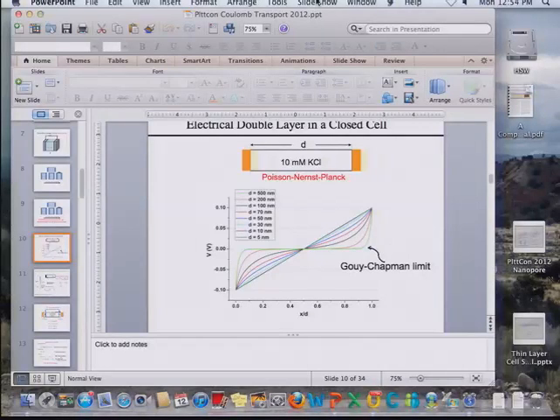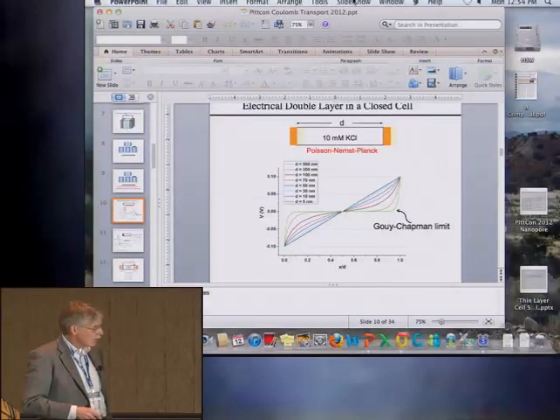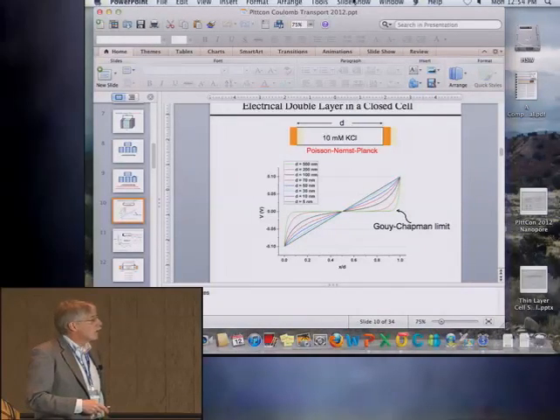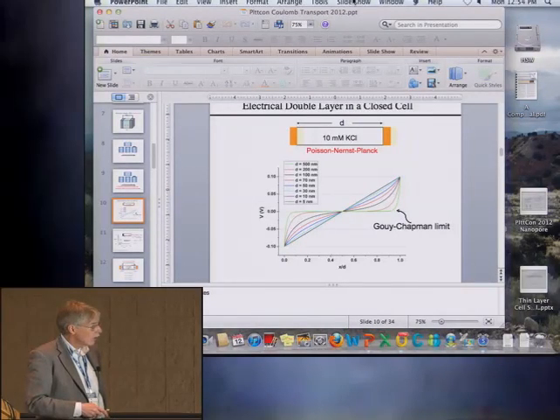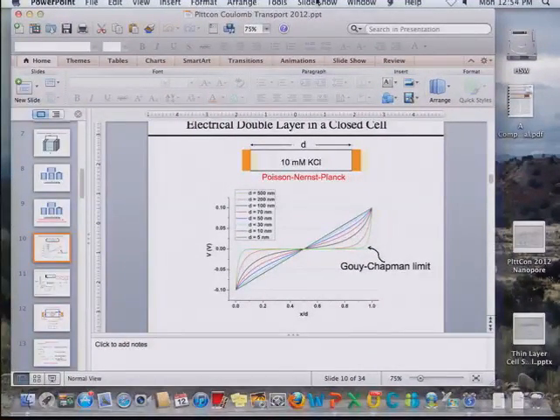All right, if you calculate the potential profile, this is voltage or potential versus distance for a cell that contains 10 millimolar potassium chloride. These are real calculations. And I'm plotting the distance across the cell normalized to the thickness of the cell. That's why they all look the same. But a very wide or large cell, 500 nanometers, is this one right here. The green curve comes down, and it's over here. This is the Gouy-Chapman limit. As you make this cell thinner and thinner, eventually down to 5 nanometers, you approach this linear potential profile that just corresponds to a capacitor. But keep in mind, I'm keeping the electrolyte concentration constant throughout these calculations.